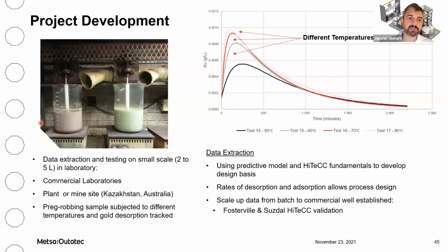To test a new concentrate, we typically use small scale, that's 2 to 5 liter laboratory tests. These can be done in any commercial laboratory, or it can also be done at the mine site, like we've done for the Kazakhstan and Australian projects. And the pre-cropped sample is subject to different temperatures, and the gold desorption is then tracked at the different temperatures.